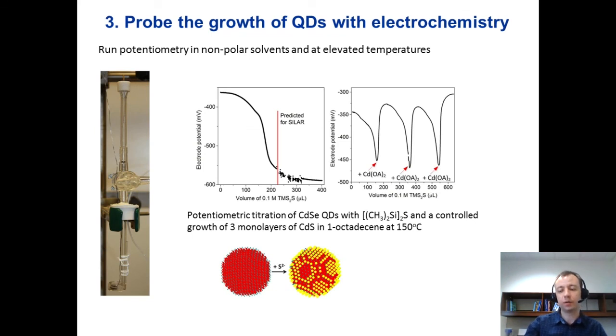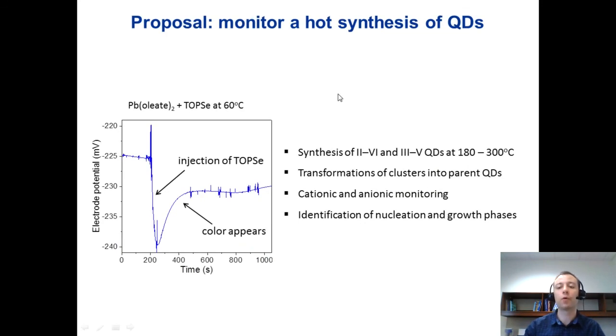Well, here we will take it even further and characterize a whole hot synthesis of quantum dots from scratch, where we load molecular precursors, heat them up, allow the crystals to nucleate and grow, and we'll monitor how the electrode potential changes. Here I'm showing some preliminary data on lead selenide at 60 degrees Celsius. Eventually, when we become more ambitious, we'll take it to cadmium selenide quantum dots at higher temperatures.